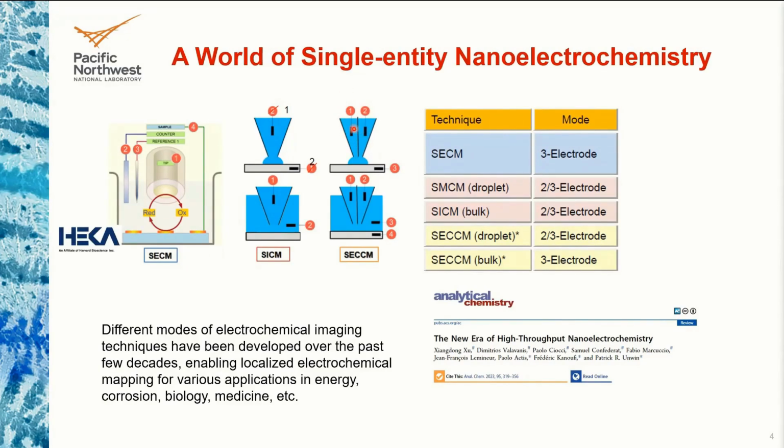One acts as a reference, the other as a counter, or both can act as pseudo counter or reference, in whatever configuration you want. It still forms a tiny meniscus at the end, and then you can land it on the surface, and it makes a perfect traditional three electrode cell. The only thing is that you are selectively exposing only the tiny electrolyte area formed by the meniscus when you land on the surface.